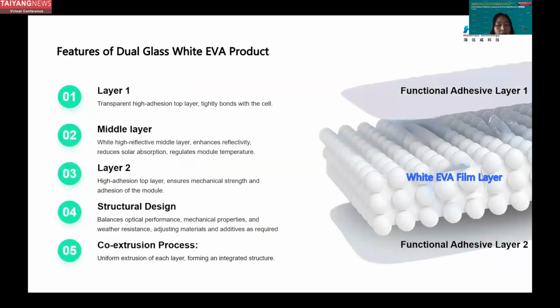Okay, this is the last part about the double glass single-sided products. That is double glass white EVA film. This film compared to our normal white EVA film, the biggest difference is that two functional layers are added on the normal white EVA film. The main purpose of these two functional layers, first is to solve the appearance of the module so that it doesn't have overflow white. The other functional layer is to have a high bonding with the glass surface.